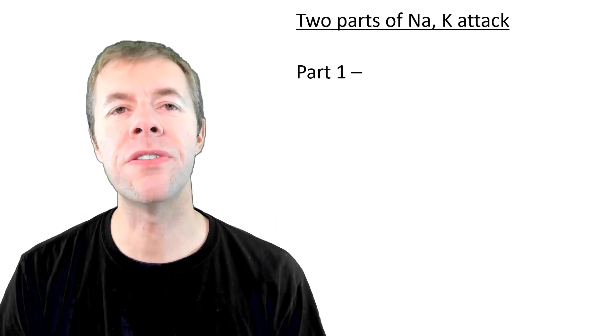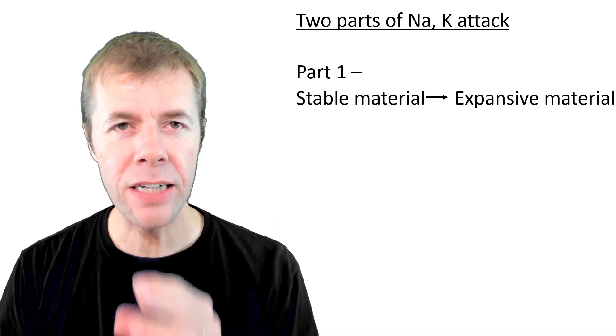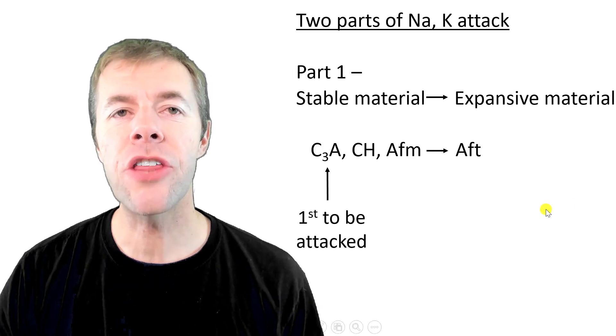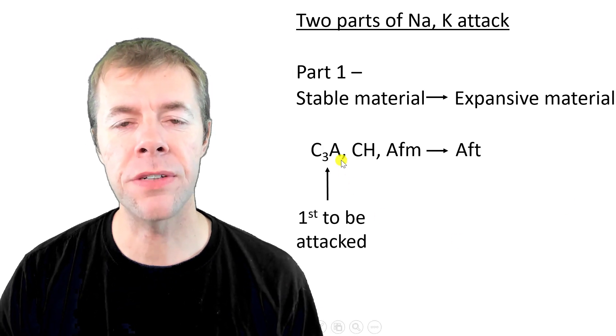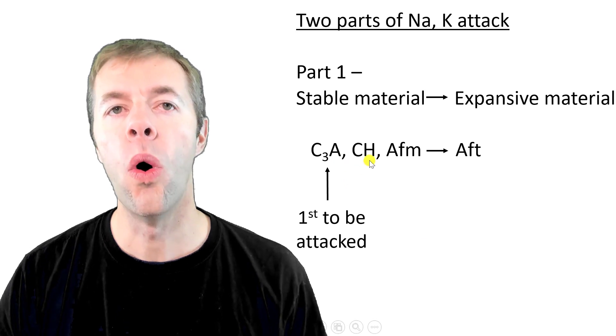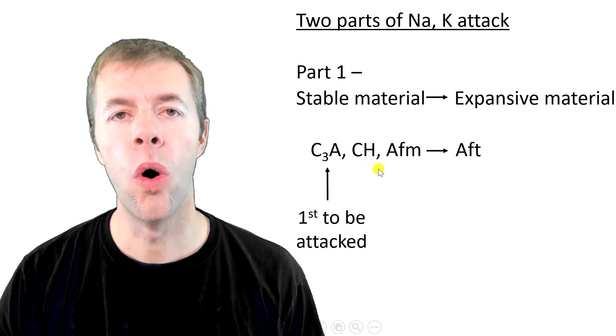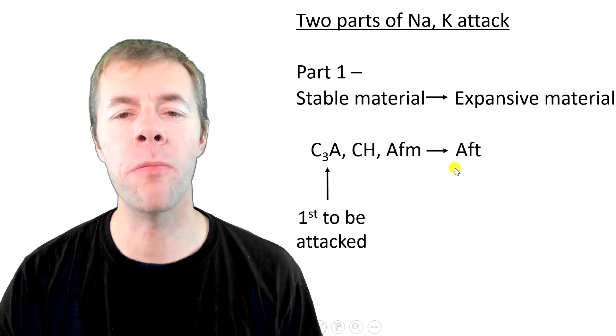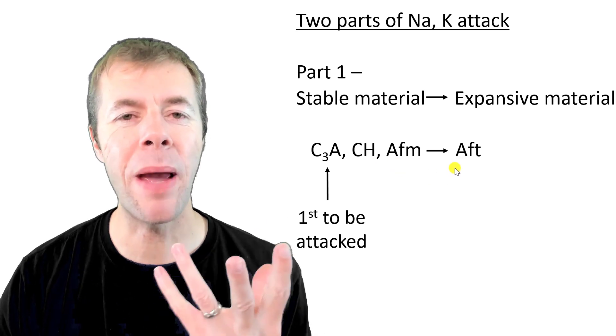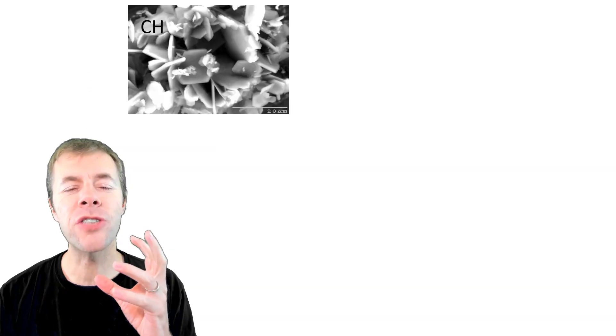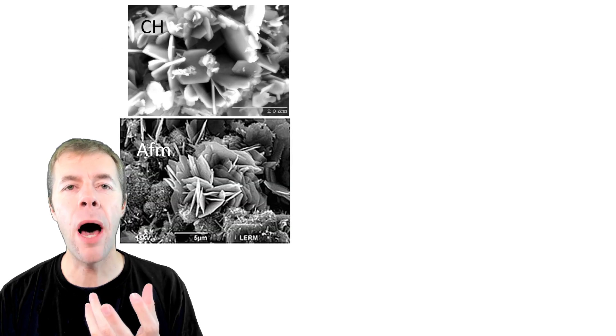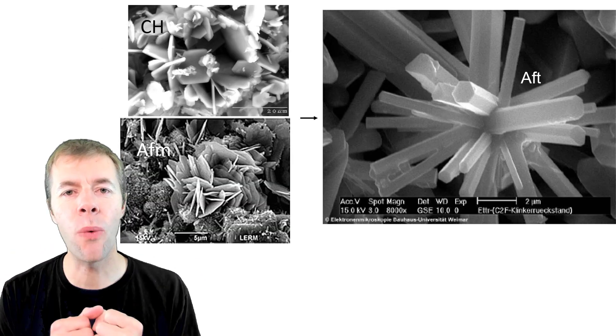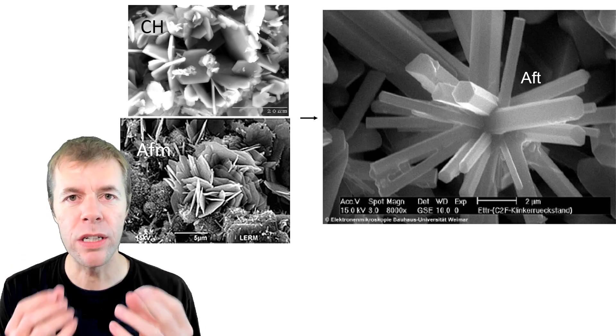In part one of this attack, the sodium or potassium salts enter the concrete and they start to attack either C3A — that's usually the first thing that's attacked — or calcium hydroxide, or monosulfoaluminate, and they form ettringite. Ettringite is expansive. Calcium hydroxide or AFM turn into this expansive crystal material on the right. There's no space for it.